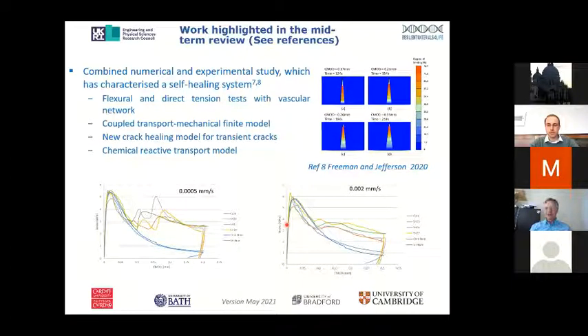And then we made sure that we could test quickly enough to effectively get the response of a control, and slowly enough, and I haven't shown the two extremes here, that you have a complete healing and then the classic re-cracking side. And then we looked at all these rates in between and tried to build a model that would naturally represent that with different crack widths. So you're right to point out that to do this, you need a fast-acting agent or a lot of time. So we chose the fast-acting agent in making the tests. Not many of our tests had durations of more than 30 minutes, many considerably less. But it did mean we could do literally hundreds of them to look at this range of parameters.